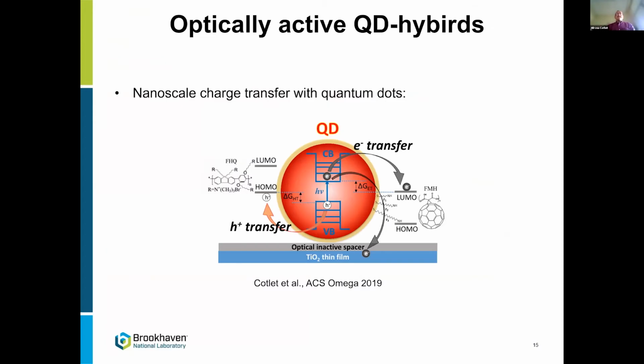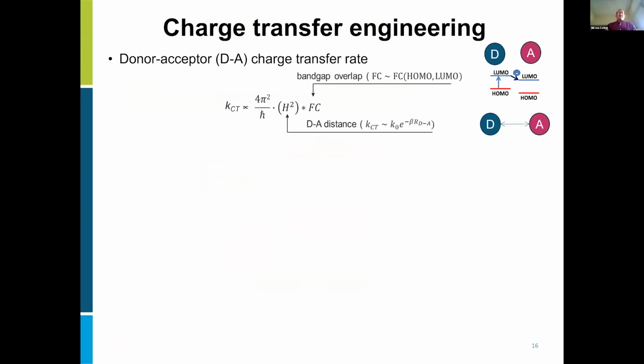So let's go for the first topic of today's talk, nanoscale charge transfer with quantum dots. The picture here shows a quantum dot with valence band, conduction band, and coupled with various acceptor materials, for example, fullerene, C60 here, where electron transfer is promoted, or with a conductive polymer, or actually with a thin film of titanium oxide. So through molecular linkers, through optically inactive spacers, through the changes that we can do to the quantum dot nanoscale structure, I'll show you how we can control the type of charge transfer and the strength of that charge transfer.